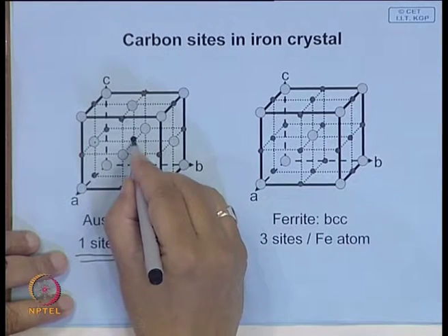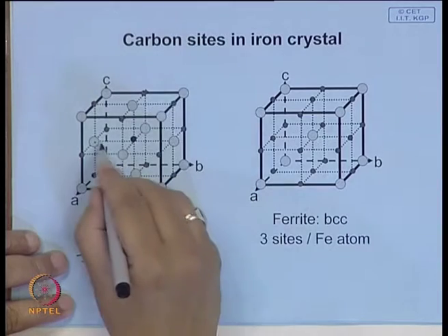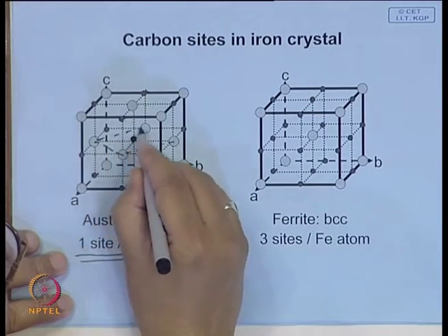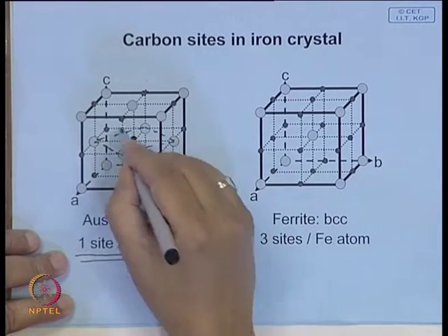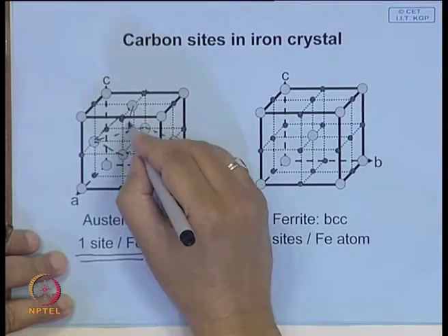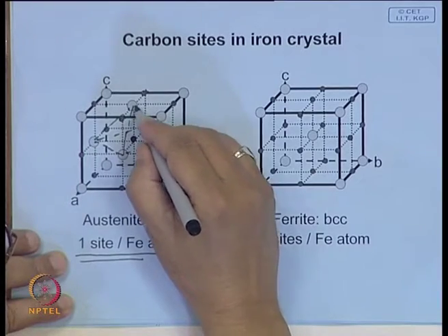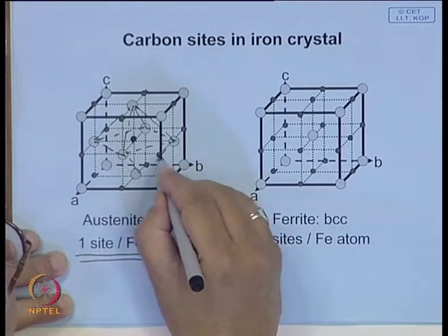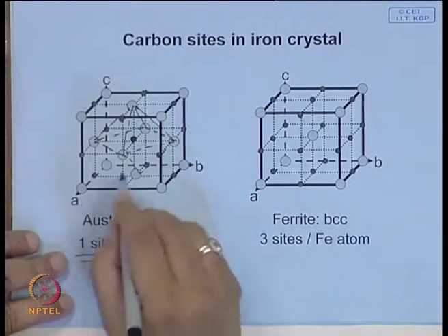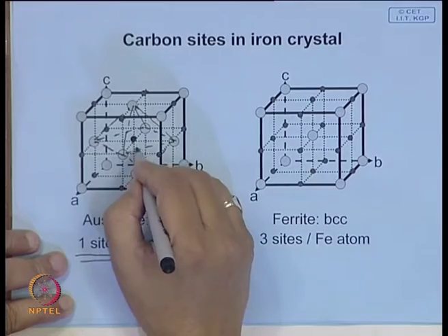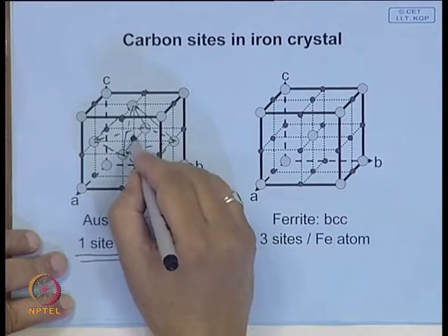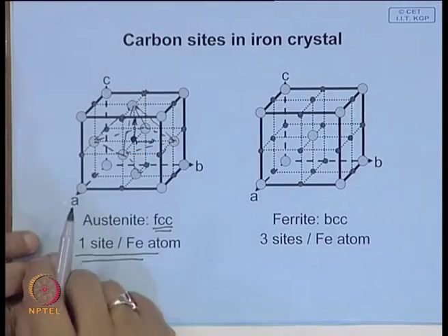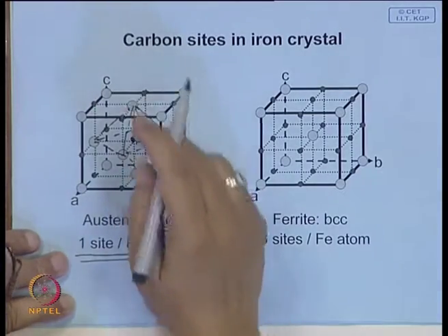Look at the atom and the site at the center of the face centered cubic. Now, if you join these, what you get is an octahedron, 8 faces. You can join similarly the bottom, and it is possible to show, in fact this was shown also, that the space in all directions, in this direction the gap, in this direction the gap, is identical.